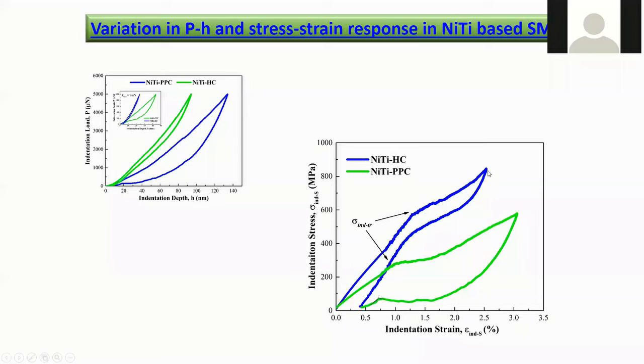The same thing can be seen for the stress-strain curve obtained from the indentation, where the precipitated one shows the curve being much lower. If you notice this carefully, you can see that even the elastic modulus part is also different. And this is related to the presence of the martensite phase in the matrix. The martensite phase, as I mentioned earlier, has a much lower elastic modulus, and that leads to variation in all kinds of properties: the recoverable strain, the elasticity, the overall strength, everything is going to change if we simply play around with the composition or the heat treatment to generate the precipitates.